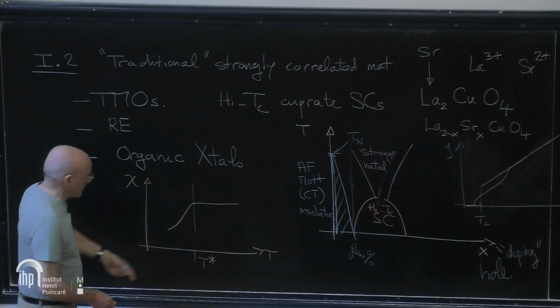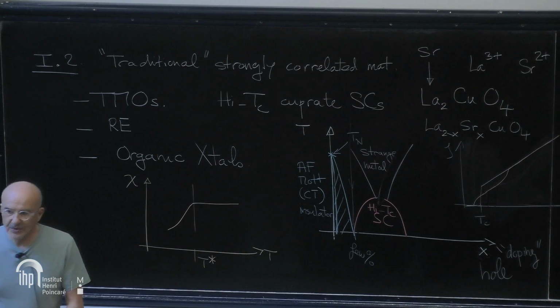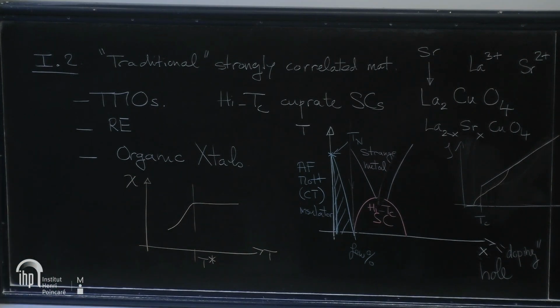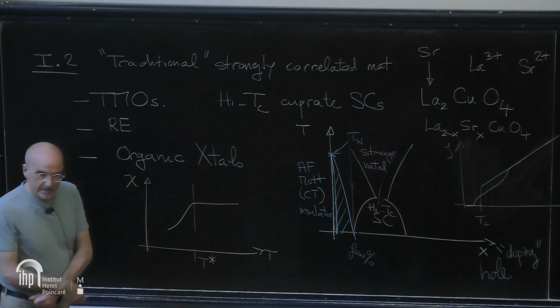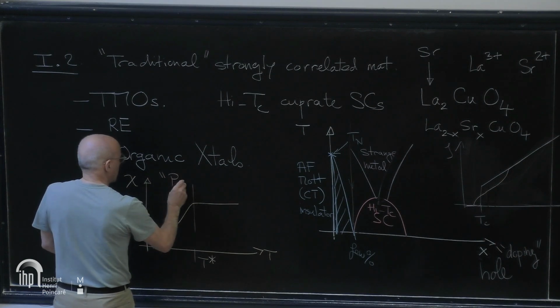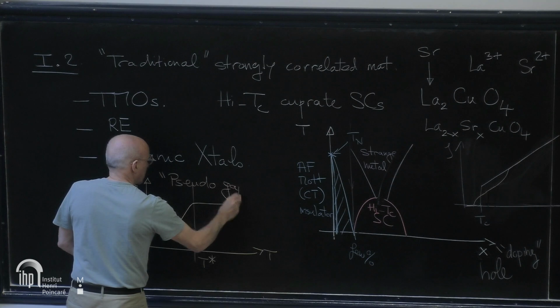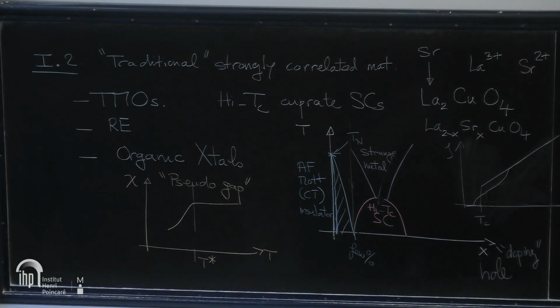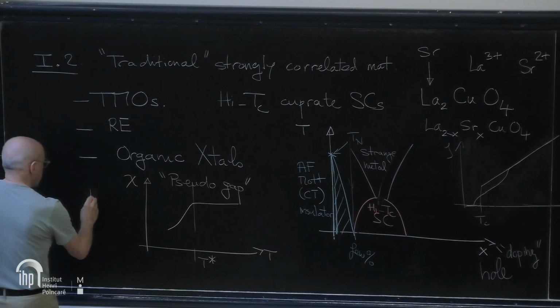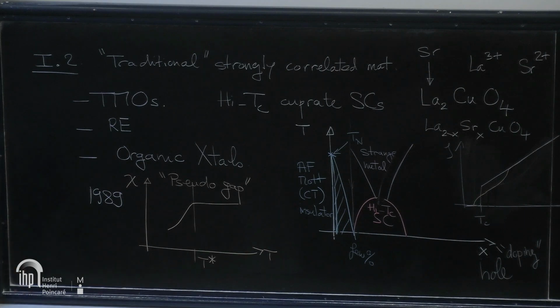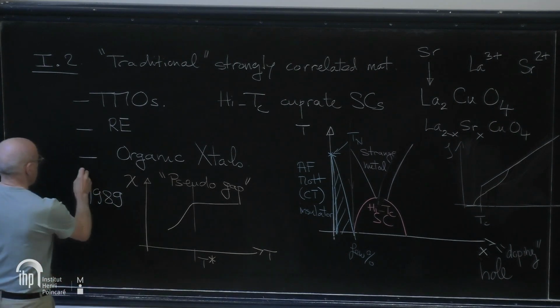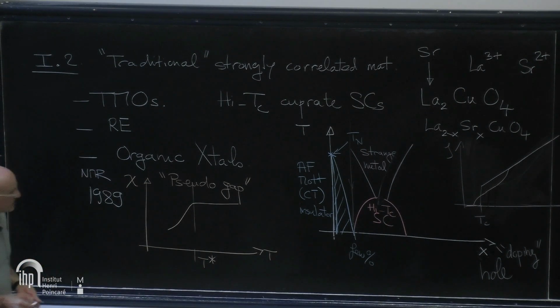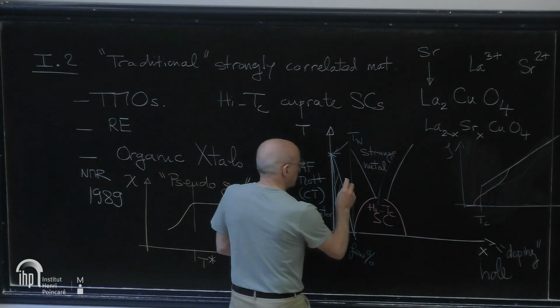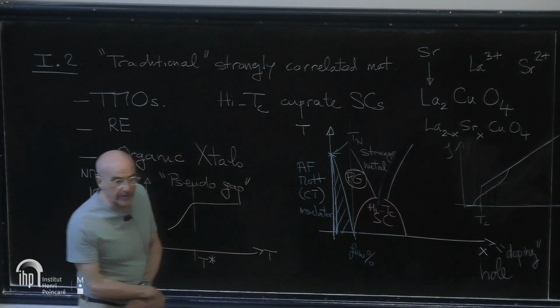It is not the behavior of a gap. In a gap system, you would expect if there is a spin gap, the susceptibility would fall to 0, right? But it doesn't quite fall to 0. It sort of diminishes upon cooling. And this is why people call this a pseudo gap. And this phenomenon was discovered back in the day in 1989 by several researchers, in particular our colleague Henri here at the University of Orsay. And this was discovered indeed by a magnetic probe, namely NMR. So this is a regime which has a pseudo gap, which is also something we want to explain.